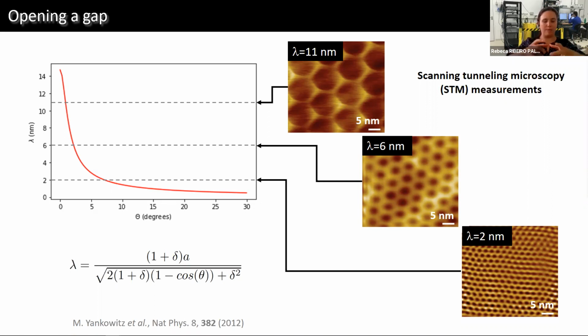In fact, what happens is that in the center of the moire, like here, graphene will stretch to match the lattice constant of boron nitride, and then it will release that strain. And where it releases this strain, you will have corrugations of graphene. These corrugations, also called solitons, will form these hexagonal shapes here. Hope that answers the question.